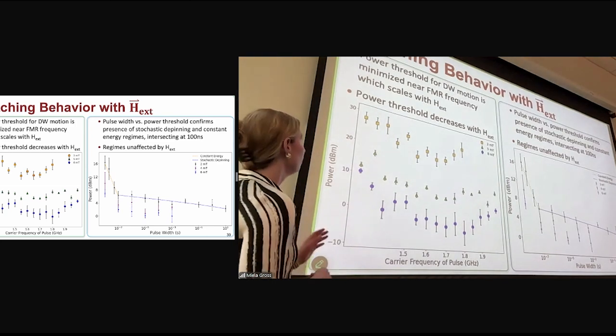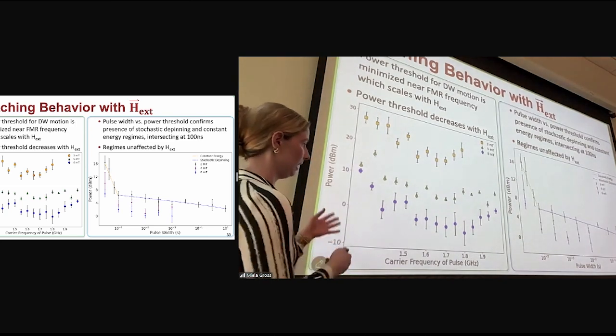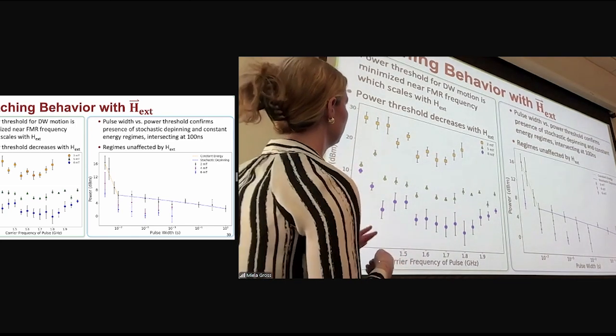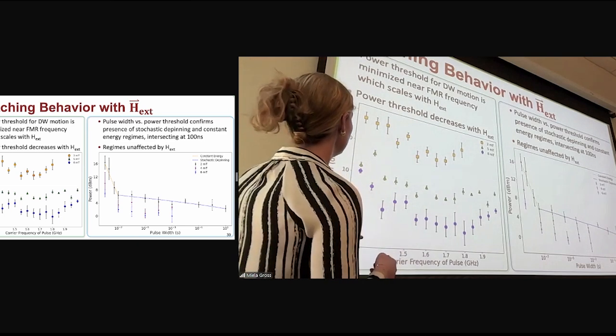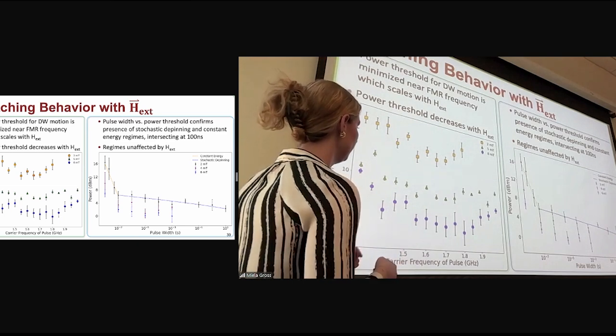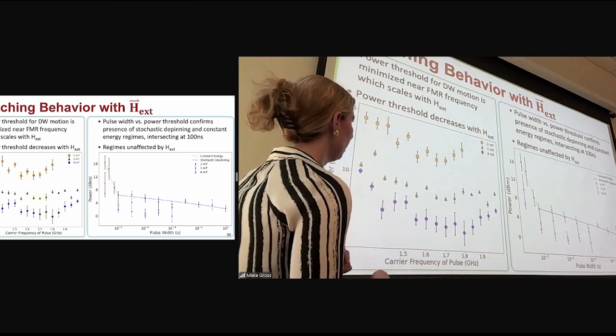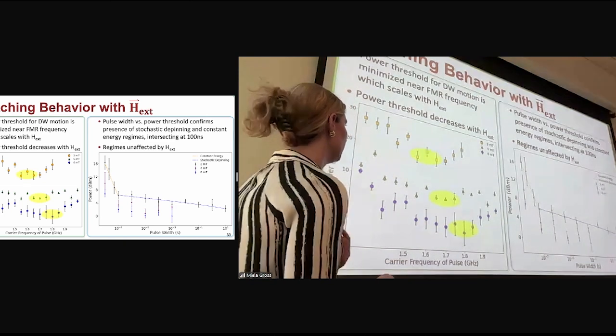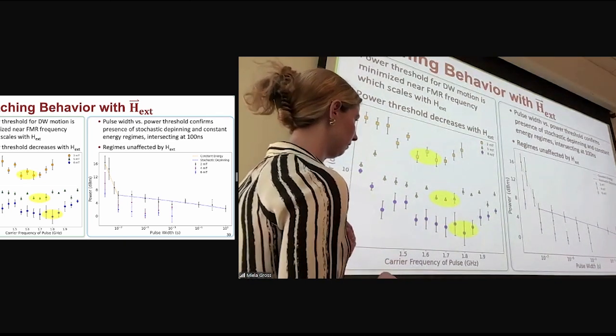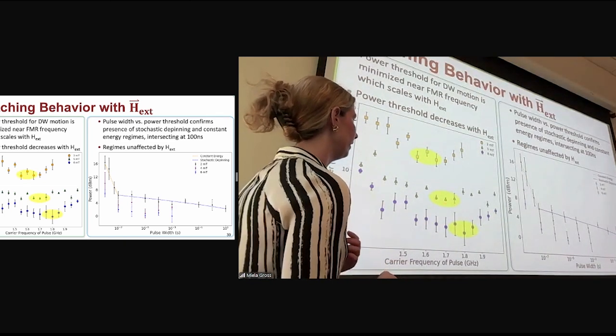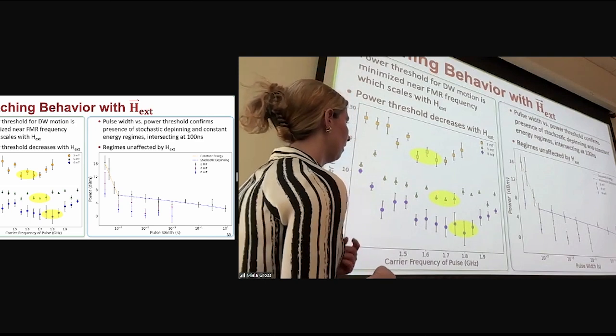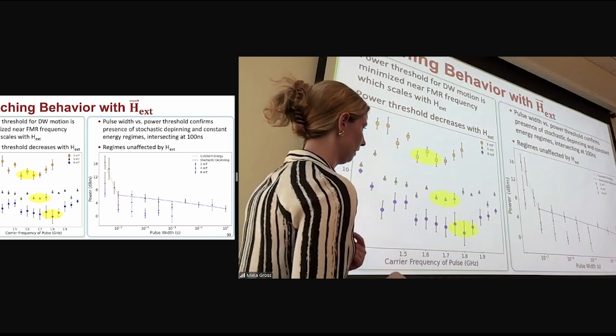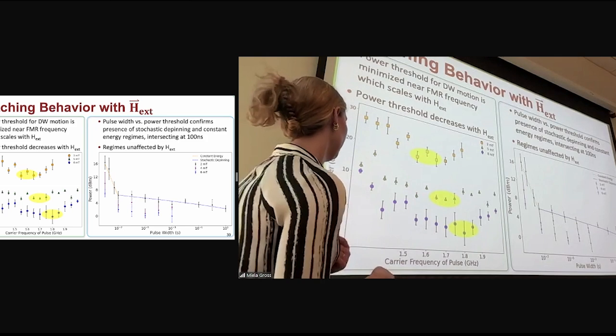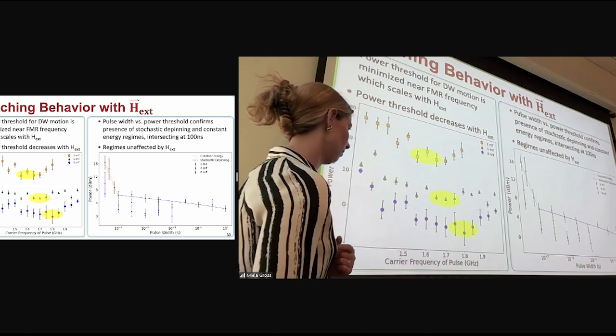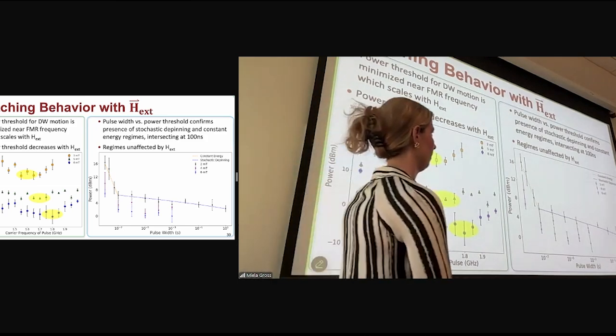But the plot on the left shows, again, we see a power threshold minimized around the FMR frequency of our device here, which was 1.5 gigahertz. But as we increase the external field applied to our device, we also see a shift in that FMR resonance frequency that corresponds to how the carrier frequency of the pulse most efficiently excites spin waves.